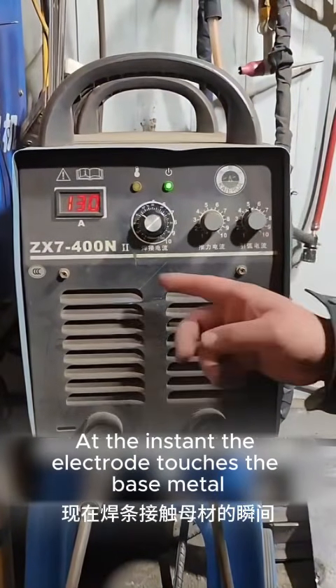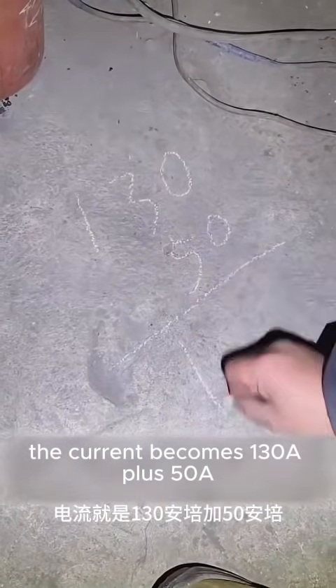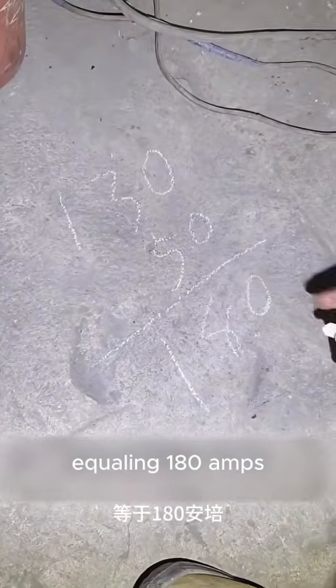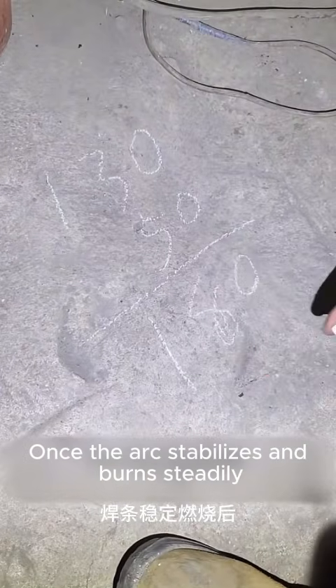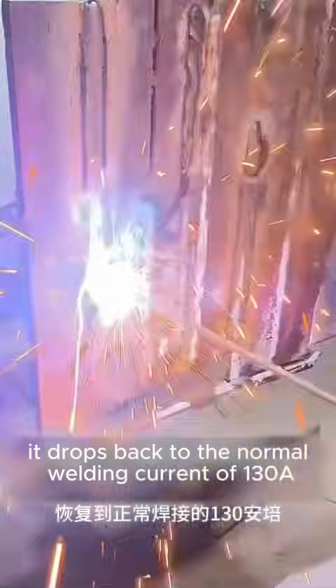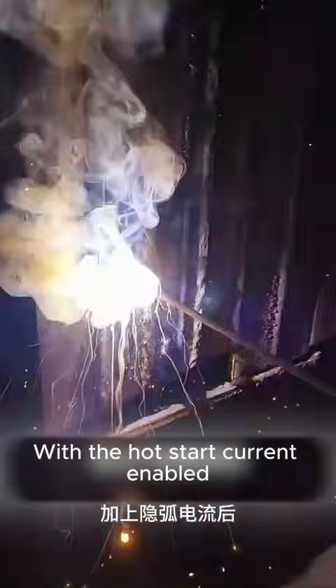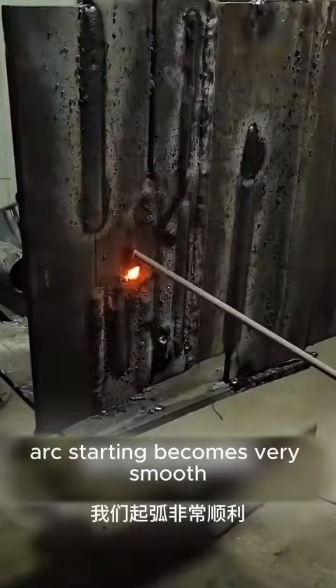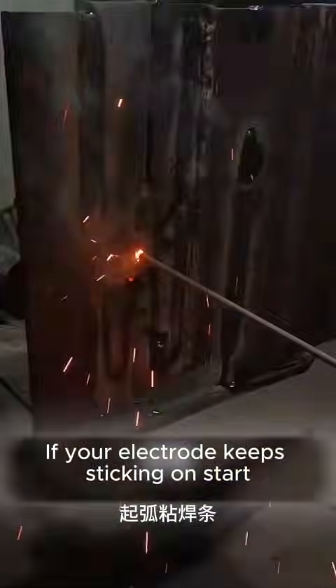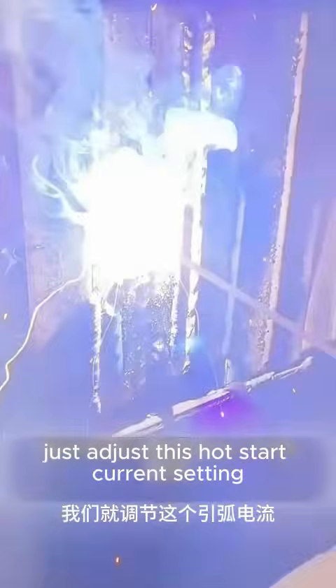At the instant the electrode touches the base metal, the current becomes 130A plus 50A, equaling 180 amps. Once the arc stabilizes and burns steadily, it drops back to the normal welding current of 130A. With the hot start current enabled, arc starting becomes very smooth, and the electrode will no longer stick. If your electrode keeps sticking on start, just adjust this hot start current setting.